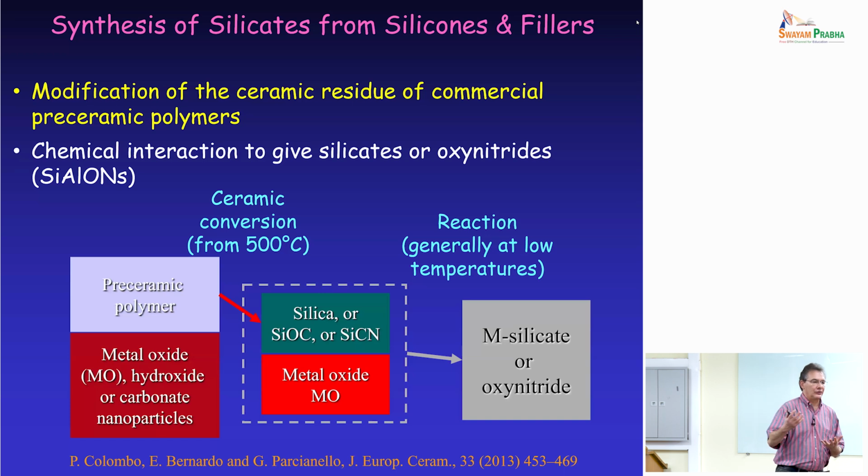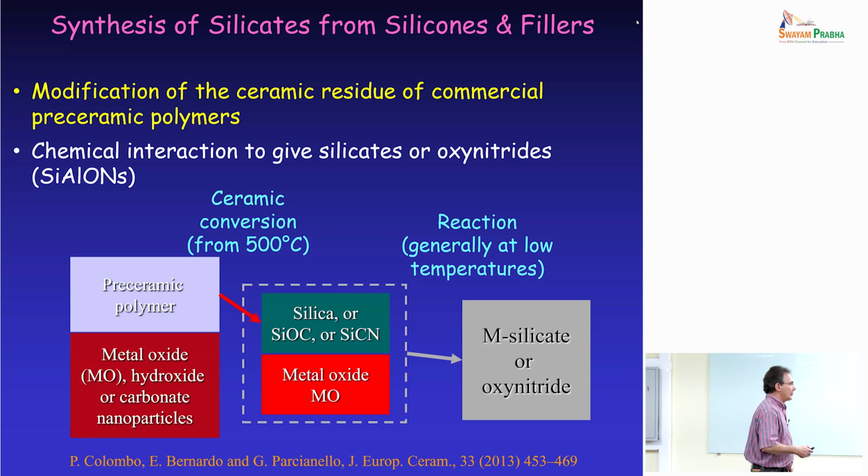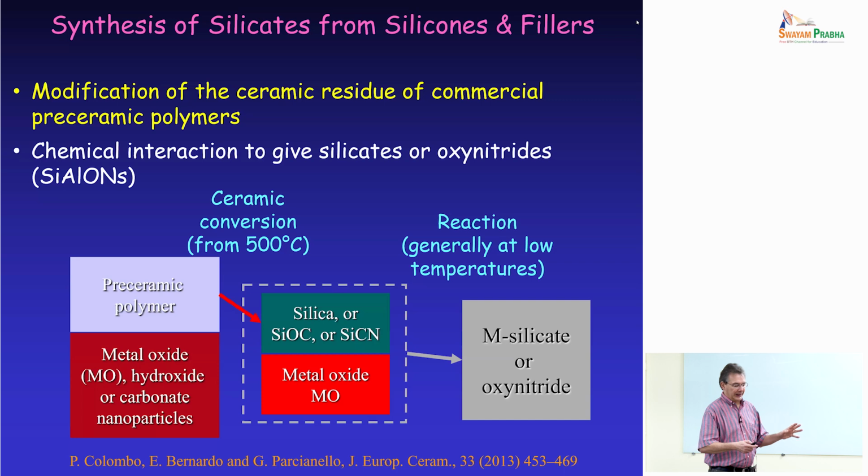If you do that, you need to achieve full mullitization, you need to go above 1500 degrees. If you use this approach, you can obtain 100% mullite at 1000 degrees. And it helps if you use a reactive form of alumina, for instance, gamma alumina, that allows you to do that. You can use it both in nanoscale or in microscale.